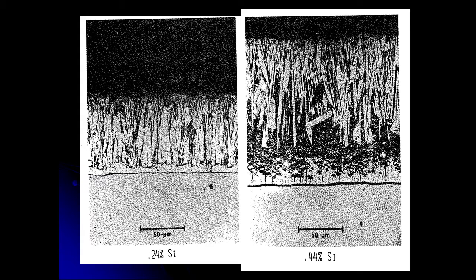That's why in the spec, if you're doing bridge pieces, the mills can give you bridge beams that have the silicon level that are correct, but it's going to cost you more money and you're going to have to wait on it. So what we've done in our spec with Illinois and a lot of DOTs, we're making sure that they sandblast the steel before it comes to the galvanizer. By sandblasting the steel, you're profiling it, and by profiling, instead of those columnar crystals going straight up, they're actually going to grow into one another.